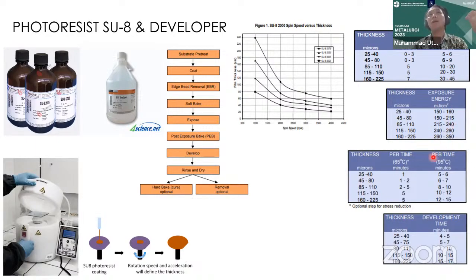of UV lights. And then after that, I do this post-exposure baking based on the thickness of the SU8 films. And then after that, we develop the SU8 using this developer. So we just put the silicon wafer into this solution, and then wait for some time, and then we can get the micro features, which we can see later on in these presentations.